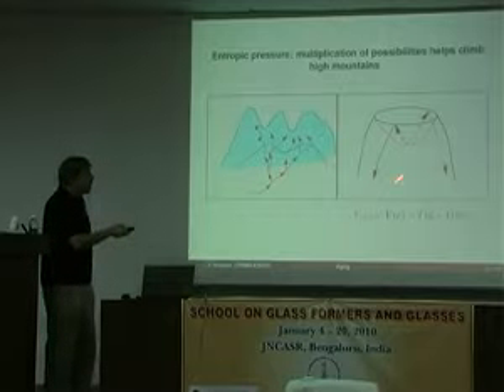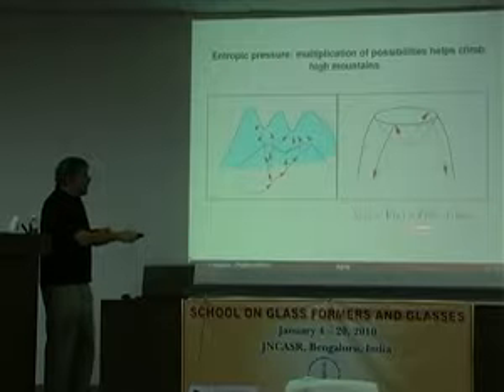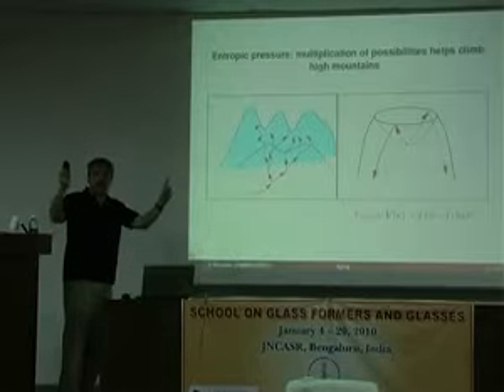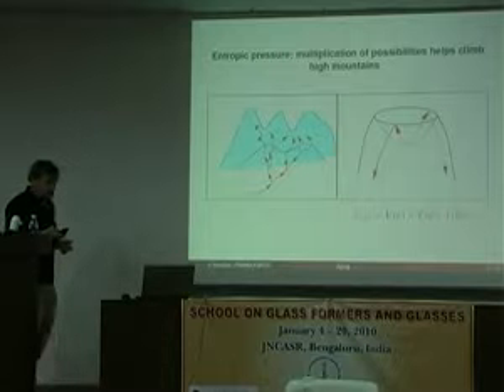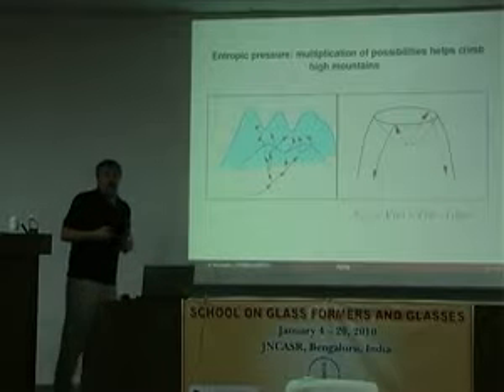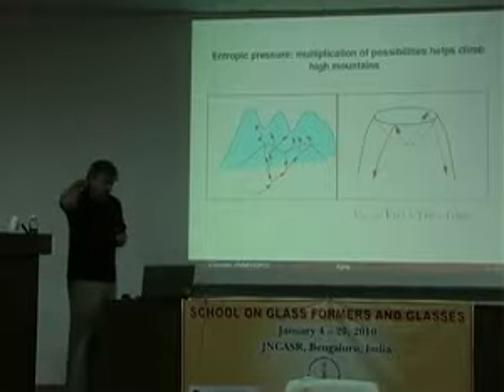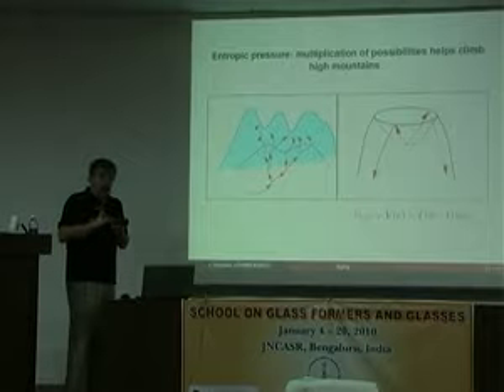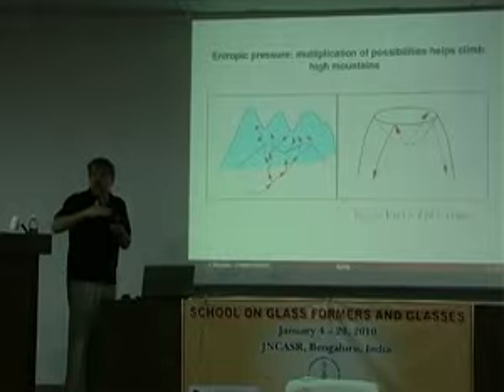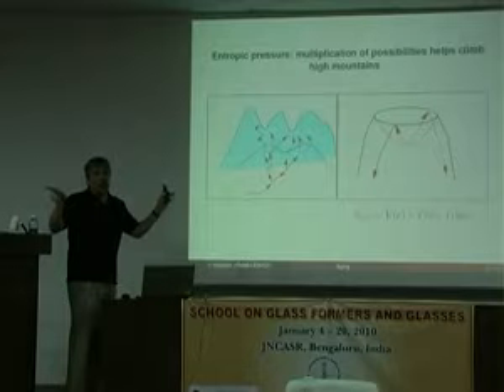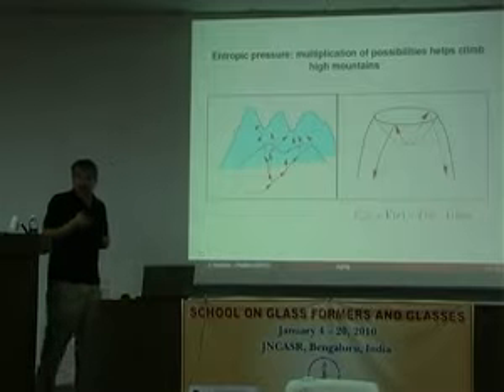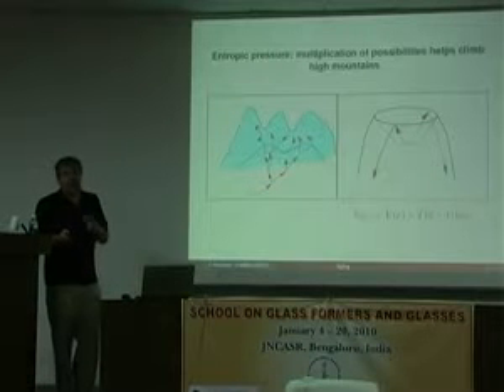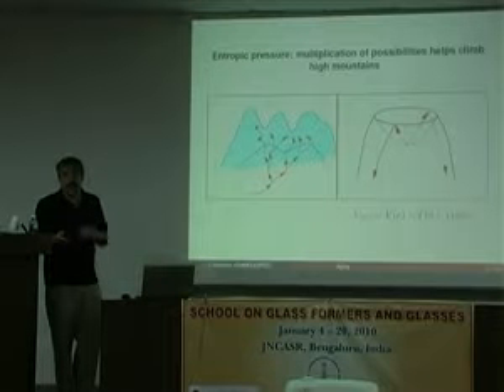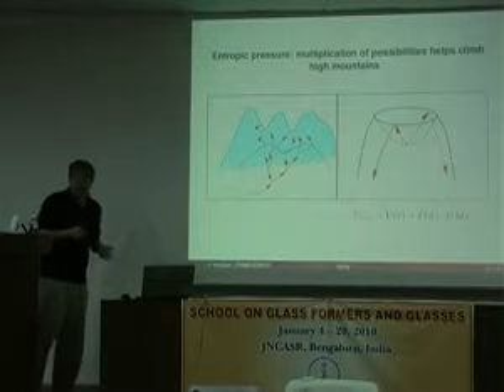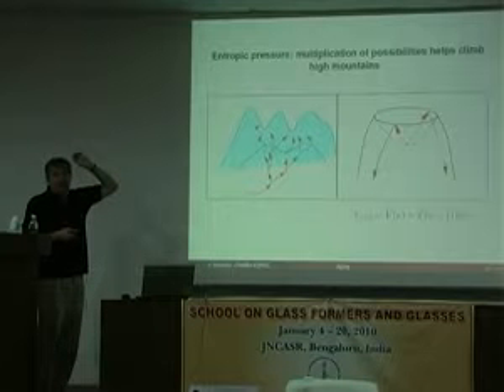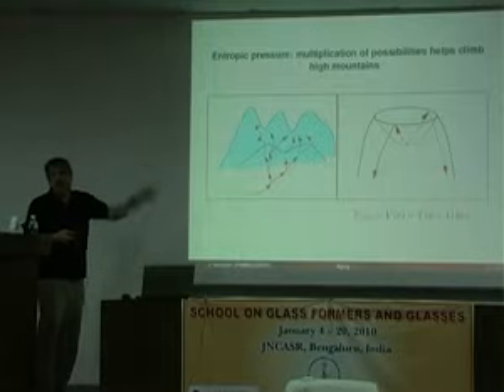So the moral of this little exercise is that having this multitude of possibilities depresses your barrier potential by a factor that is precisely the entropy of the barrier. So there you see it in a very concrete example. So, to recap, the nucleation argument, now you can do it taking into account this, and now you can say that even if you are not in a situation where your free energy of your state is extensively higher, so you don't have a free energy density that is higher, if in any case you have an exponential number of options to go, then you don't stay. So a metastable state that is in competition with an exponential number of cousins of the same free energy density will not survive dynamically forever. So these are two reasons why a glass cannot be something that is merely hanging on a metastable state that is living forever.